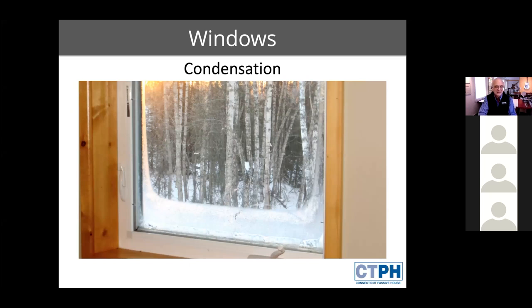Here's a double glazed insulated window in a northern climate. It's clearly cold outside. It's had multiple hits of cold, if you will. The outside is a sheet of ice down along the lower portion, and the inside is a sheet of ice along the lower portion. A couple of things to note. Note that in the middle of the glass, there is not a condensation problem. And remember that all of the American manufacturers will give you an R value of their windows in the center of the glass. This is a great example of the center of the glass is usually not the problem. The problem has to do with the thermal bridge around that perimeter. That's an aluminum spacer and in this case, a PVC frame. It conducts heat so effectively that you end up with situations like this.